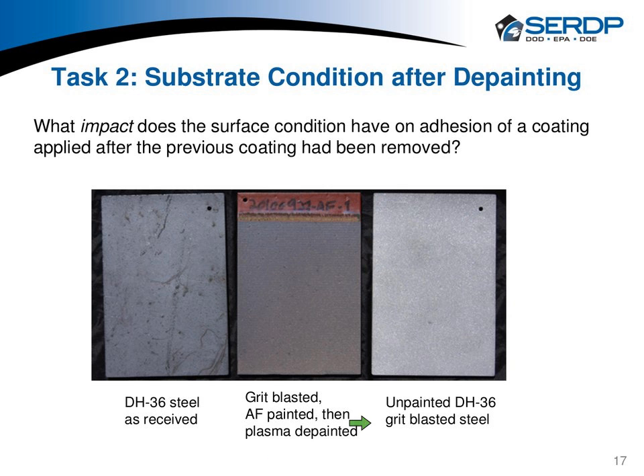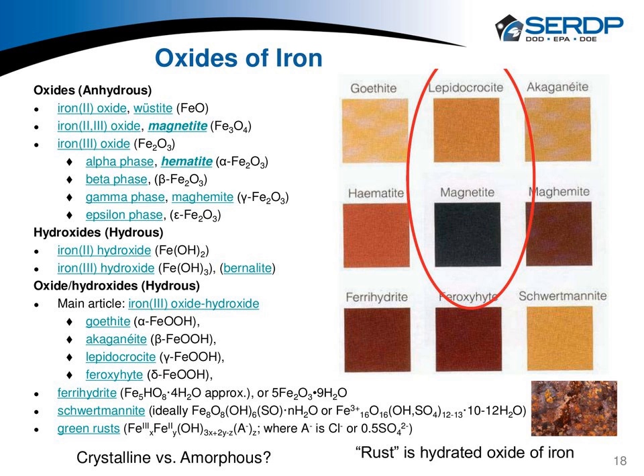So what is the visual difference? Why do we have a seemingly darker surface here as opposed to a grit blast? Well, to help understand that, we have to look at the chemistry of iron, or more specifically iron oxides. After all, we're looking at the surface of the iron that has been exposed at some point. Now, in the case of grit blasting, there are a lot of different types of media that are used, but all of them essentially wear through the surface of whatever's on the steel until they get down to base metal. And now we're down to iron 0.